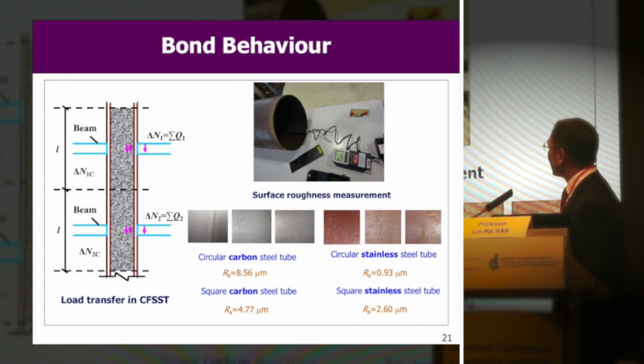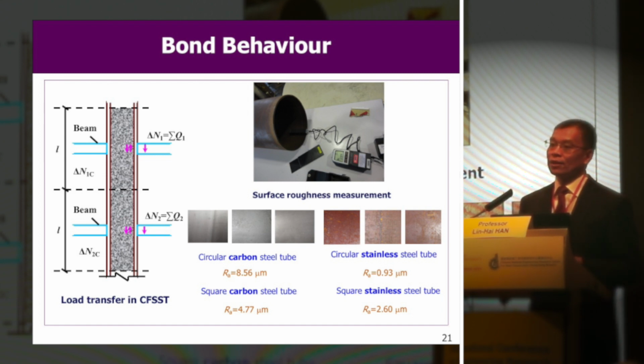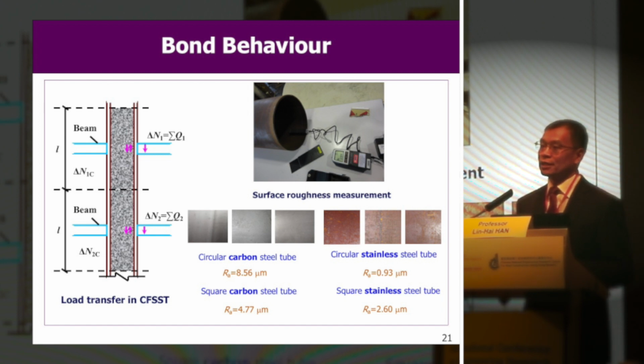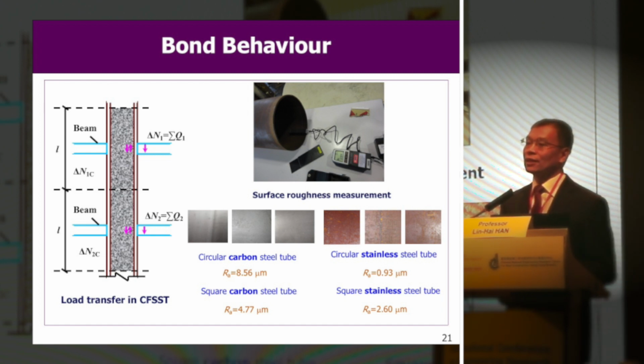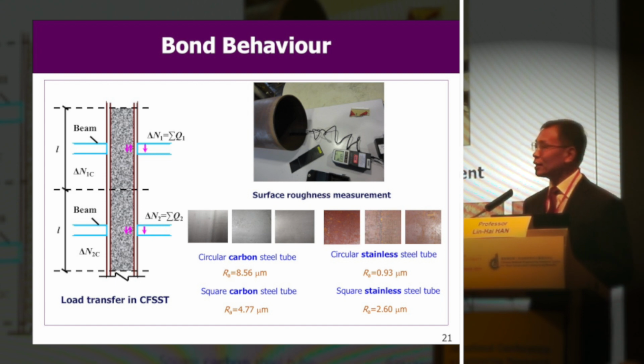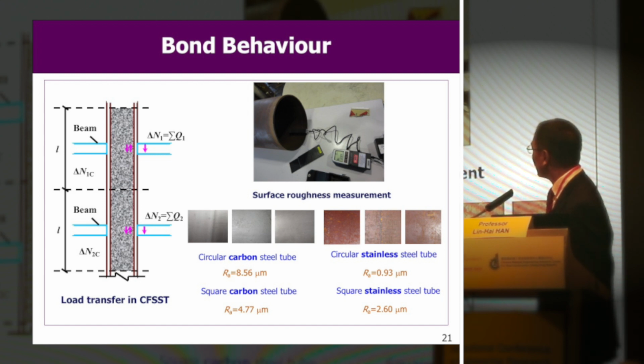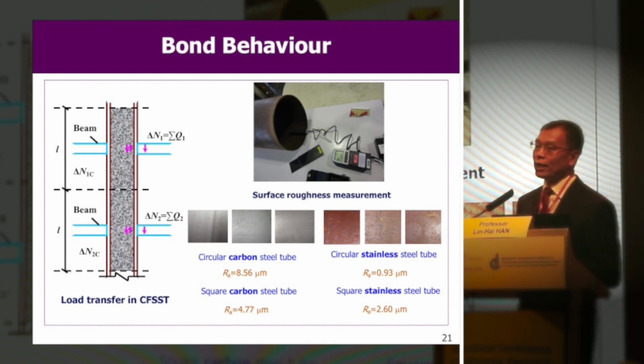Because the bond between the core concrete and the outer steel tube is critically important for this type of composite structure, to ensure that the core concrete and the outer steel tube can work together during the loading process. So the bond behavior is crucially important. Our first step is to check the bond strength between the stainless steel tube and the core concrete. Actually, one of the most significant differences between carbon steel and stainless steel is the roughness of the steel surface. So we measured the surface very carefully to compare the differences between the two types of tubes.